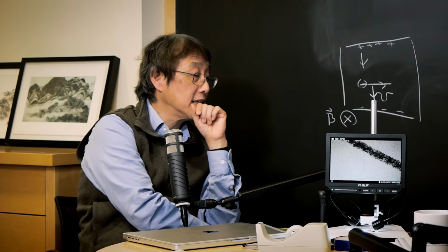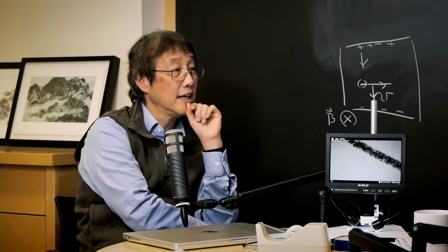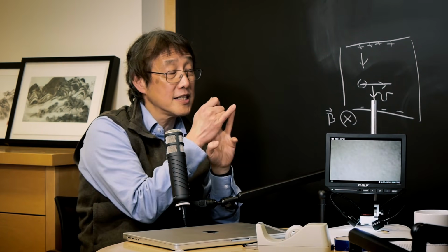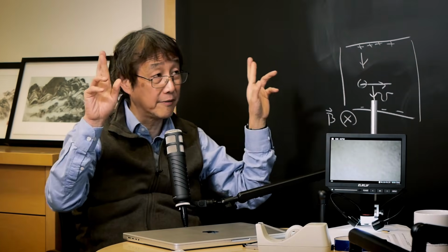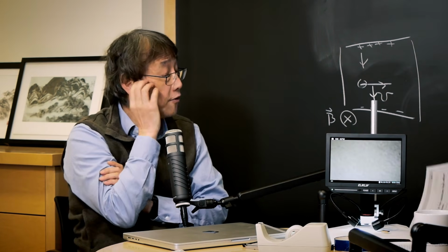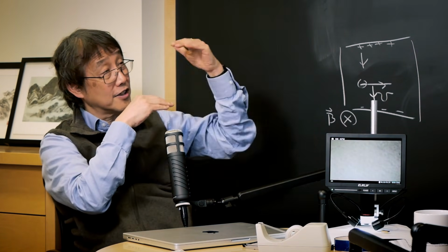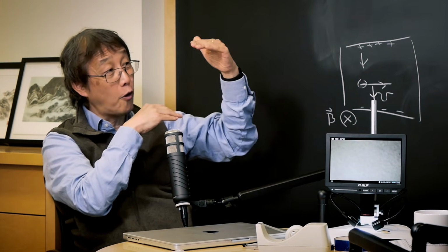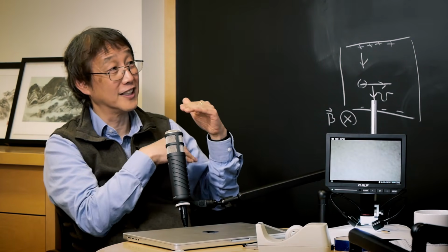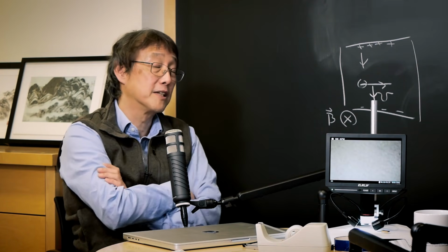What you are seeing here is basically that the integer increases by 4, like 2, and the next comes as 6 and 10. Which means that each Landau level is degenerate by 4. That degeneracy of 4 is related to spin and two valleys. In other words, I have two Dirac dispersions in the graphene band structure, and that comes to 4. But the interesting part is that I can see the Landau levels increase by 4, but why does it start not from 4, but from 2? That's the important part. It increases by 4, but half-integer shifted, and that is related to the Berry phase, related to the spin-half spinors there.